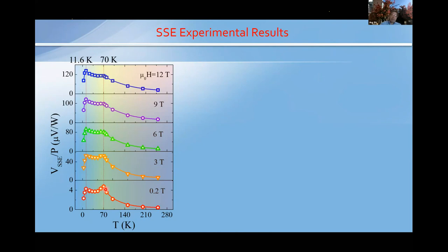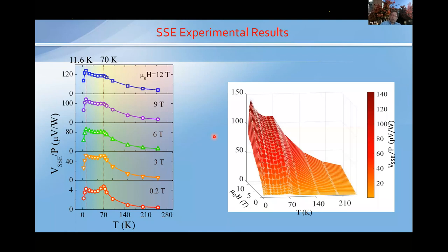When we increase the field, this high temperature peak gradually broadens. This is reminiscent of critical phenomena: when you have a continuous phase transition and you apply and increase a magnetic field, you get a broadened peak in the vicinity of the transition temperature. The other peak, located at 12 K, stays roughly at the same position. If I plot all the data together, it shows similar characteristics.